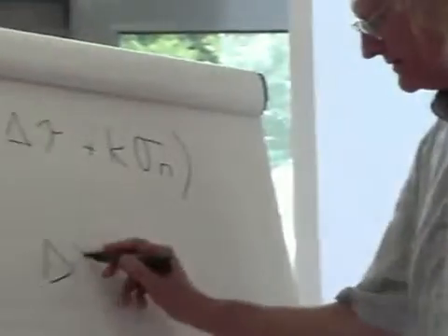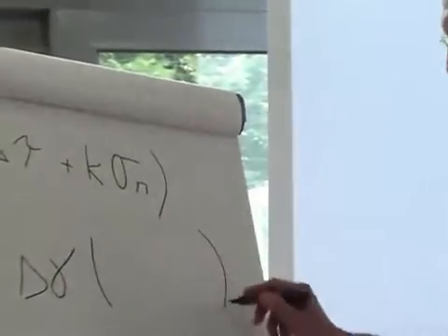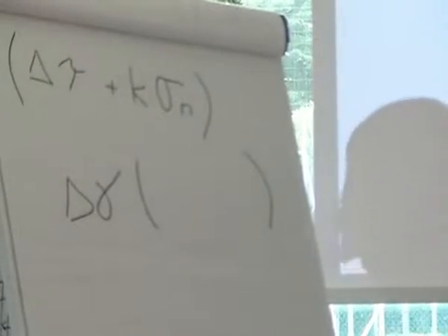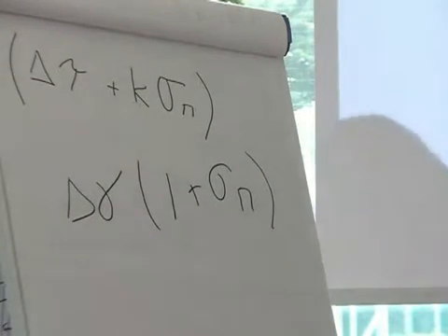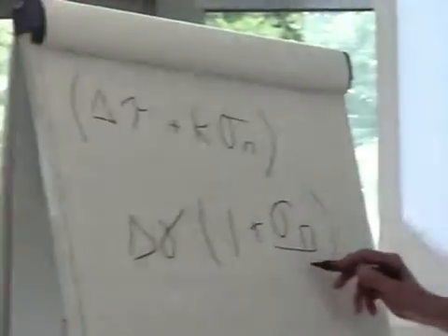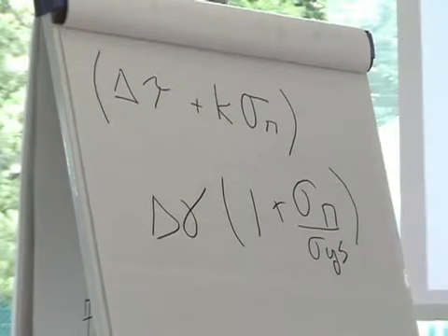And so I sat down at my desk and said, okay, just take this. So start with the shear strain and multiply it by the normal strain, or the normal stress. If you multiply it, well, of course, that gives you energy, and that's not right. And I said, oh, just do this. Just multiply it by that. And then he said, oh, it's got the wrong units. He said, let's just normalize this by dividing this by the yield strength. And I said, okay, that looks pretty good, go try it. Probably all of a 10-minute discussion. That's how the parameter actually came about.